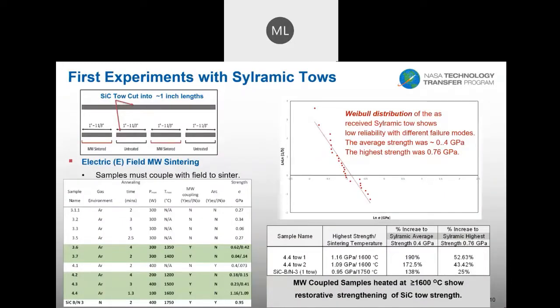So when we first started our more rigorous experiments, this is where we were working out a lot of the processing parameters, aligning the fibers using different gases. But one of the first things we did is we took some silicon carbide tow, and we cut that into one-inch to one-and-a-third-inch sections, and then every other piece of tow was heat treated in the microwave. We did that because the structure of the fibers, and individual filaments within a tow, is going to vary along the length of the material. So we wanted to get a good representative of the microstructure changes to see if this was really working.